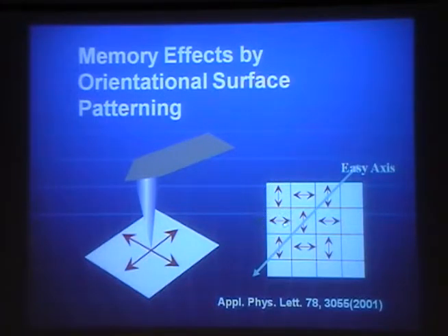And you can now reverse one of the orientations. This 90-degree orientation may be reversed to minus 90 degrees. Then you have 0 or plus minus 90 degrees divided by 2, meaning minus 45 degrees. Then you get an orientation this way. So these two are the possible average orientations that you can achieve on this particular pattern.